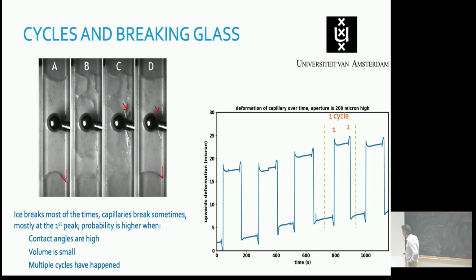And so, a very long story short. What you see here, A, B, C, D, is 4 stages of a single cycle. This is the liquid. This is the solid, and what you see is that actually the ice itself breaks, and that makes sense because the ice is actually weaker than the glass. But there's also a break in the glass, and we can identify the breaks in the glass when we remelt the ice, and then this fracture remains.